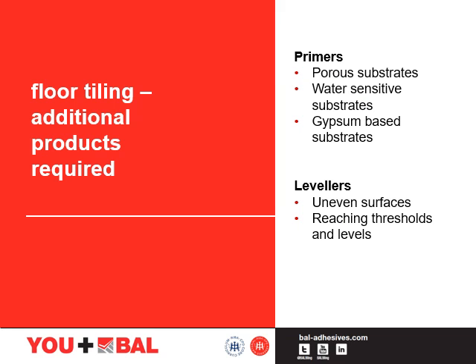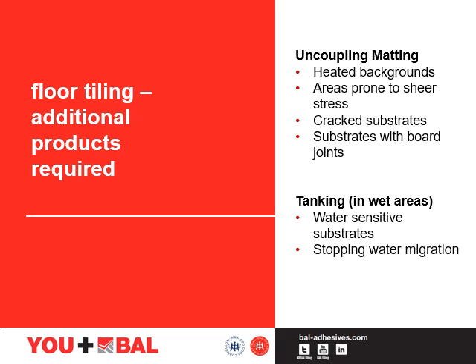Primers are used for porous substrates, water sensitive substrates and gypsum-based substrates. On porous substrates it regulates the absorption. On water sensitive substrates it can stop too much water going into the screed and damaging it. On gypsum-based substrates it stops a reaction called ettringite, where a gypsum-based product comes in contact with wet cement and we get salts growing between the two. Levellers should always be used where we have an uneven surface that is not SR1. An uncoupling mat should always be used in areas with heated background, prone to shear stress, cracked substrates and substrates with board joints such as plywood. Tanking in wet areas should always be specified in water sensitive substrate areas, as it also stops water migration into the fabric of the building.